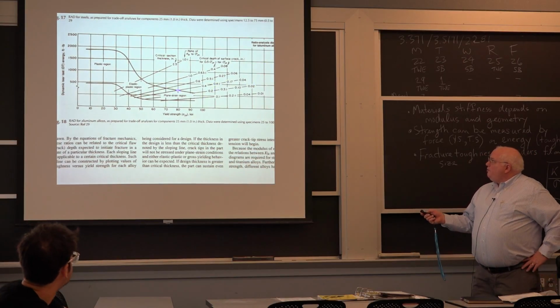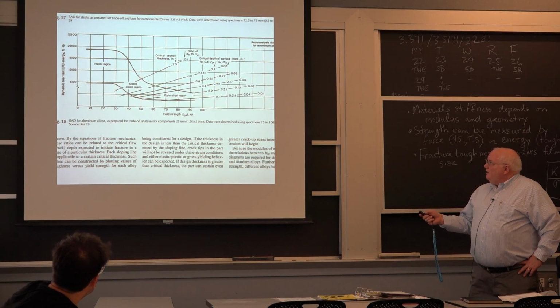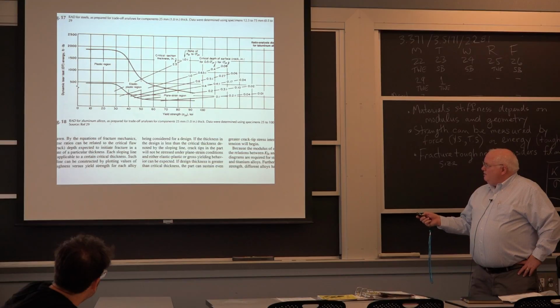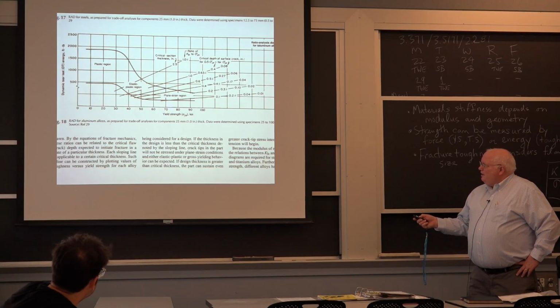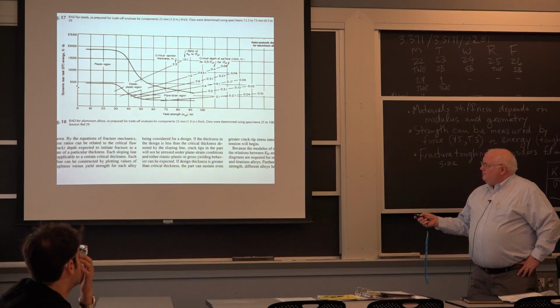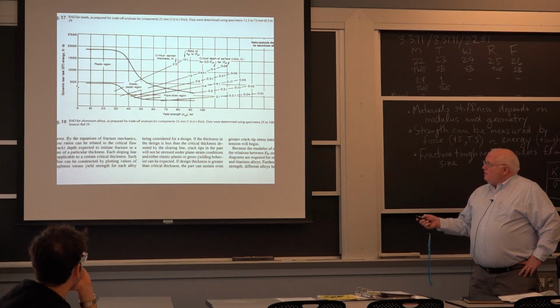And here's a ratio analysis diagram that he did for aluminum alloys, and you have a similar type of technological limit. Your low strength aluminums, but remember the steels went out to 300 KSI. The yield strength of a high strength aluminum like an aircraft wing is 70 to 80 KSI. Low strength aluminum like beer can stock is up here in the plastic region. We have to form it.